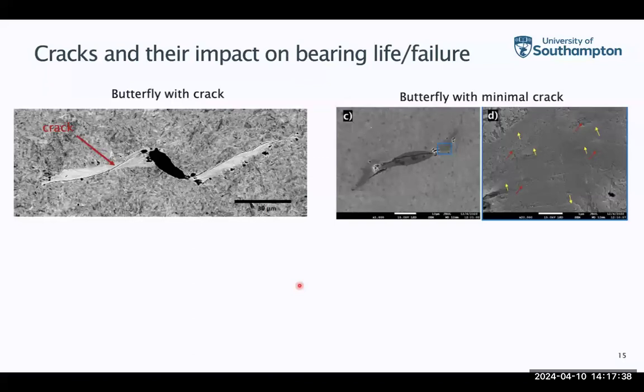With butterflies, it was a bit strange, because some of them have cracks in the wing. You can see here, a very obvious crack in the wing, but some of them don't have cracks, like this wing. We don't see any cracks in the wing, or major cracks as we normally call them. And butterflies don't normally lead to early failures as well. We tried to find out why.